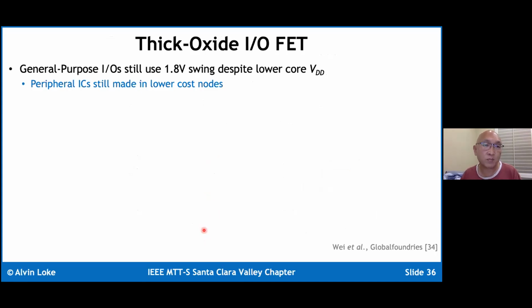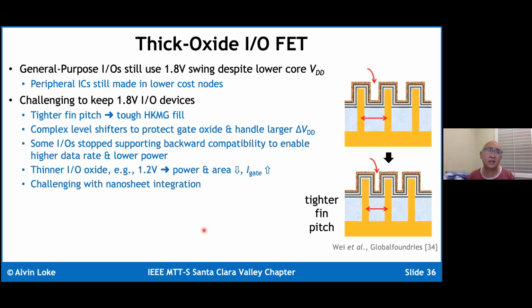Okay, let's talk a little bit about thick oxide IO FETs. So general purpose IOs still use a 1.8 volt swing, despite the core VDD aggressively going down. It's simply because these advanced node ICs still need to talk with peripheral ICs that are made in lower cost nodes. It is increasingly challenging to keep the 1.8 volt devices. Why? Because as you're making the fin pitch tighter, it's making life more difficult to actually fill your replacement metal gate, HighK metal gate process. And with a thicker oxide, that's naturally more challenging.